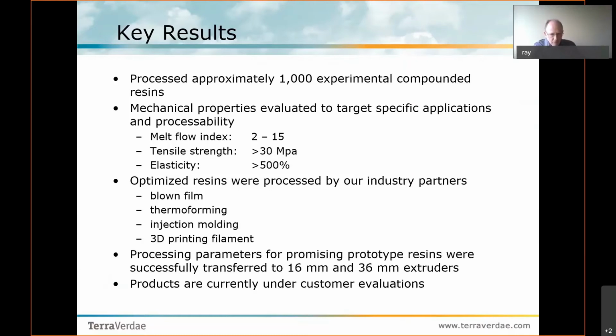Our optimized resins: after we did all the screening, we passed on our process and our formulations to our partners, and we were successful in producing blown film samples. We thermoformed product, injection molding products, as well as a 3D printing filament. We were able to transfer the processing parameters of the promising resins to larger extruders, so they were able to use our information and successfully go ahead with 16 millimeter and 36 millimeter extruder operations and produce hundreds of kgs of our pilot scale resins. And these products are currently under evaluation by our customers.